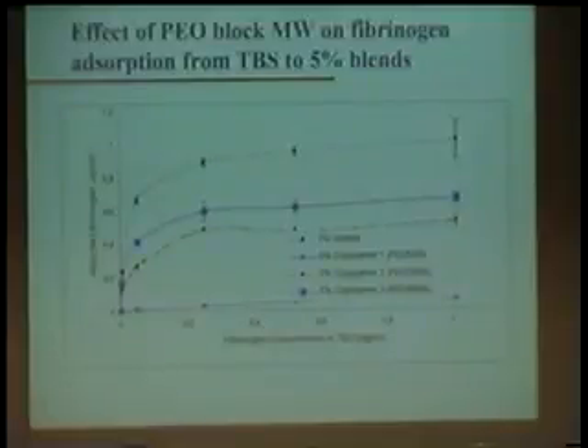This is an inverse dependence of protein resistance on molecular weight of the PEO, and I say inverse because other people who've worked in this area using grafted PEO on the surface find the opposite, that as the molecular weight goes up, the surface becomes more effectively non-fouling. But this is not a grafted surface, so maybe it isn't surprising that the dependence is different. We don't have the explanation for why at this point.